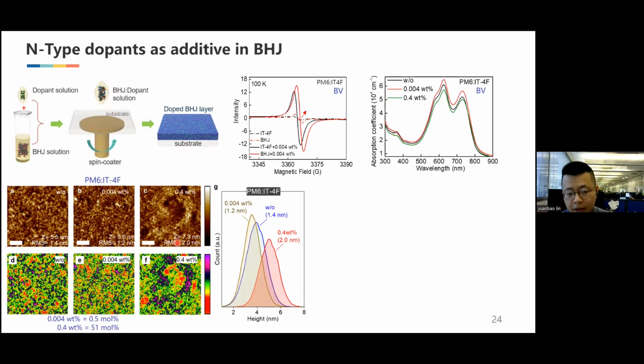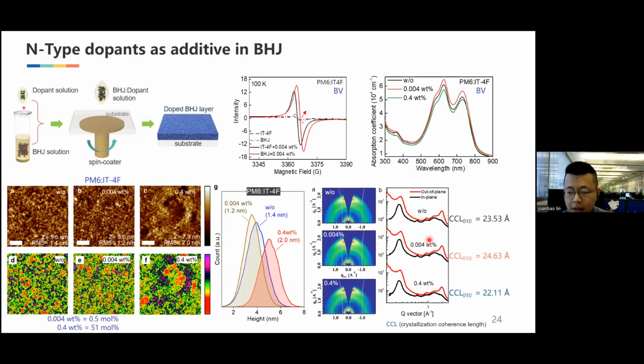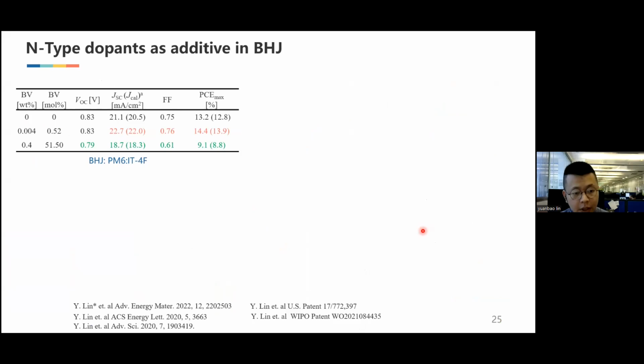If we add too much dopant, the donor-acceptor phase separation of the bulk heterojunction will be enhanced. But if we add a little bit of dopant, it becomes smoother, and the pi-pi stacking crystallinity is enhanced with these dopants. As for the performance, at that time we tried PM6:IT-4F, and as a result, low doping can enhance the PCE and photocurrent.